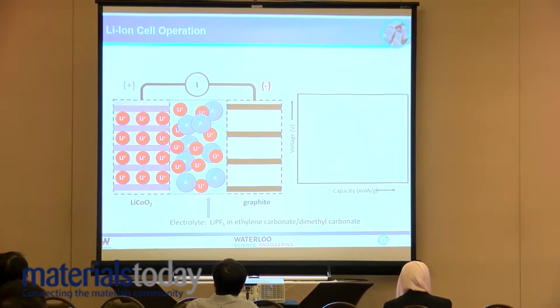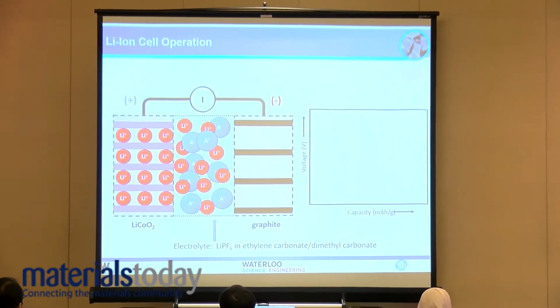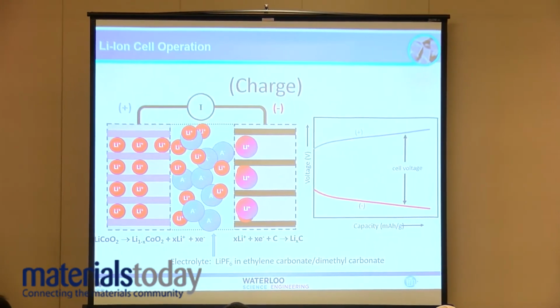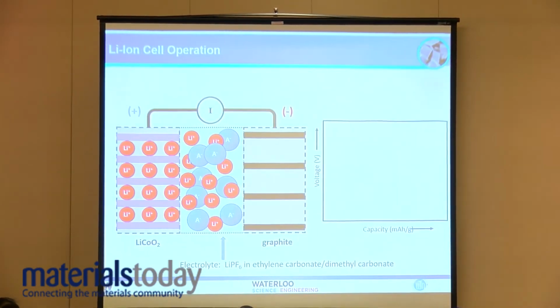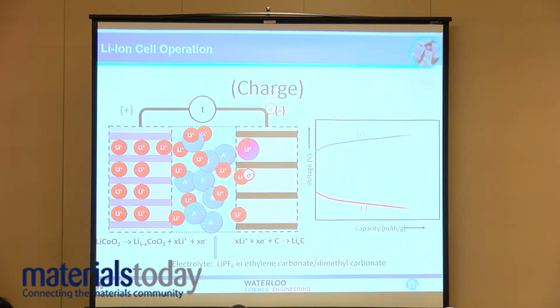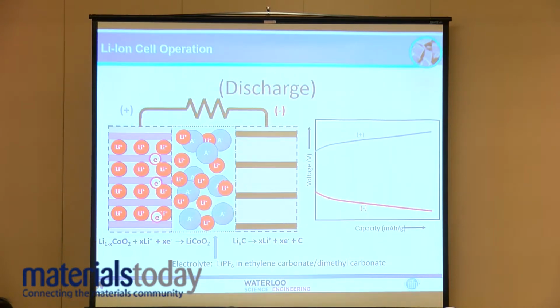So for those of you who are not familiar with how a typical lithium-ion battery works, probably most of you are, but just in case. On the charge aspect of the cell, the lithium ions are placed into the layers of typically a graphitic type of carbon, and they are deintercalated from typically a layered metal oxide, and lithium cobalt oxide is the favorite. It's still used in the Dreamliner, although other metals have since replaced cobalt. And on the subsequent discharge of the cell, this process is basically reversed. So it's called a double intercalation system. The lithium ions either lie between the layers of the carbon or between the layers of the oxide.